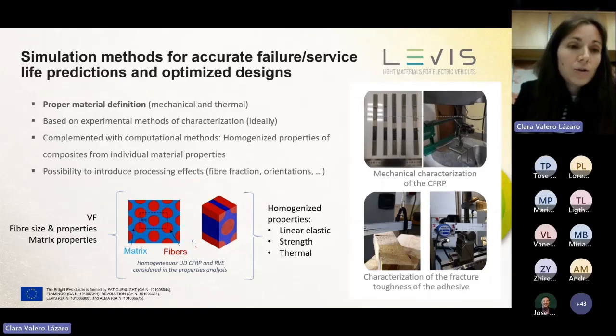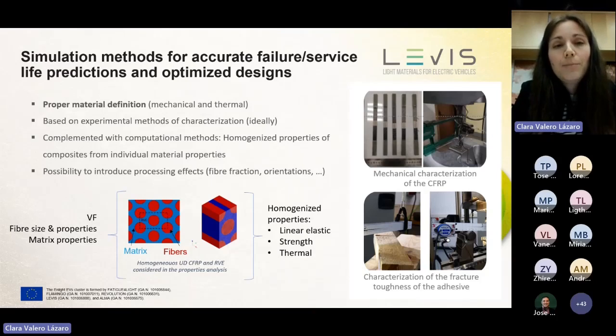And we can also introduce effects created or observed in the process simulations. For example, we have observed that in some cases the fibers reoriented, or that depending on the manufacturing conditions there is going to be, for example, porosity and so on. So we can modify these conditions in order to have a better, let's say,